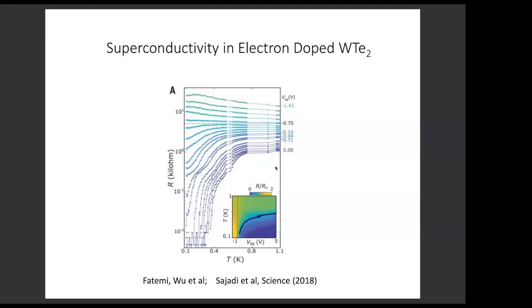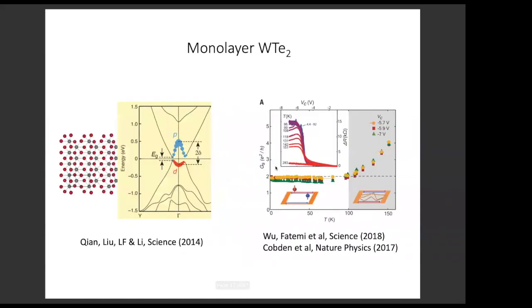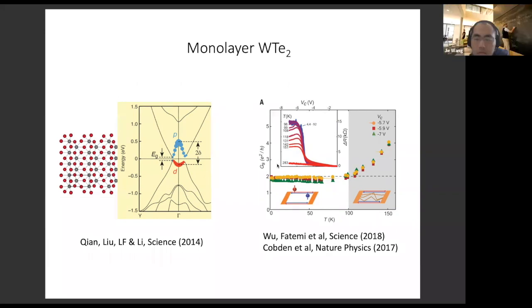And also what's interesting, if you go to the previous slide, in the conduction band of tungsten ditelluride, you actually see that there are two electron valleys. So although this system does not have hexagonal lattice symmetry, one feature that it has is that there are two valleys in the conduction band. So electron doping would create a two-valley electron gas. At low density, you expect the system to be a two-valley electron gas, just like what our toy model does.